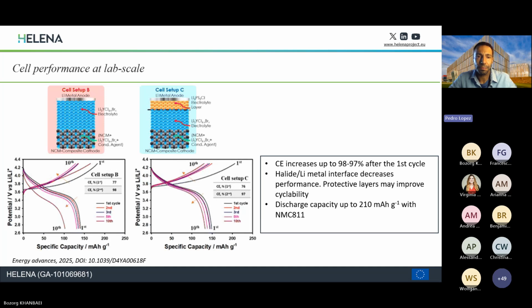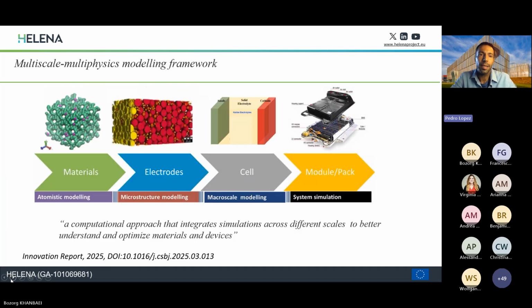So within the project, we have a specific task on developing these protective layers to improve the compatibility between the lithium metal anode and the solid electrolyte. We've also shown that we can increase even further the capacity from this almost 150 milliampere hour per gram, up to 210 milliampere hours per gram when we replace the NMC 622 by NMC 811 with a higher theoretical capacity. So please, next slide.